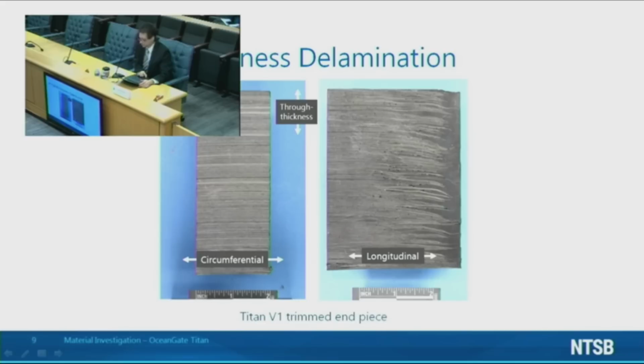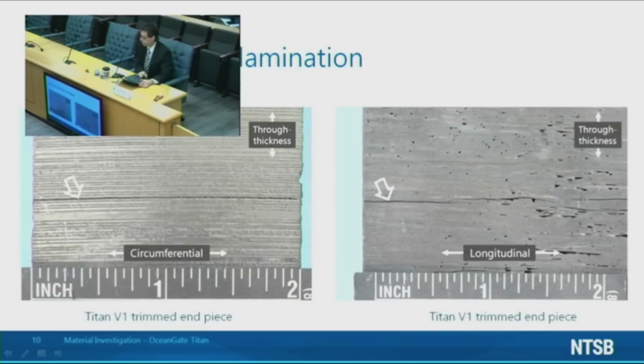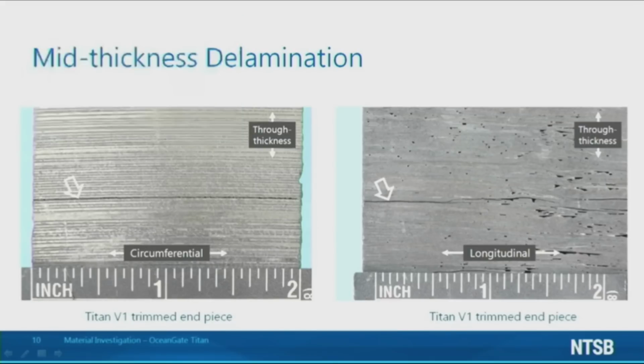Investigators had the opportunity to examine a leftover piece of the Titan V1 hull. The hull was originally manufactured with excess material at both ends, and then the hull was trimmed to size. The leftover piece was trimmed excess material from one of those ends. The piece contained voids and delaminations. One notable delamination was located about mid-thickness and is shown from different directions in these two images, as indicated by the white arrows.